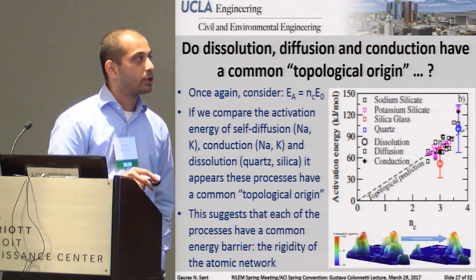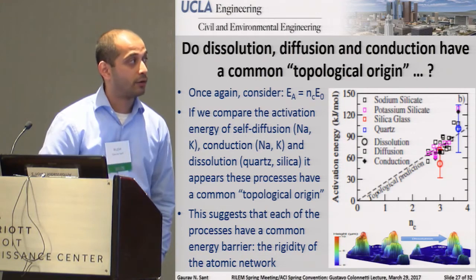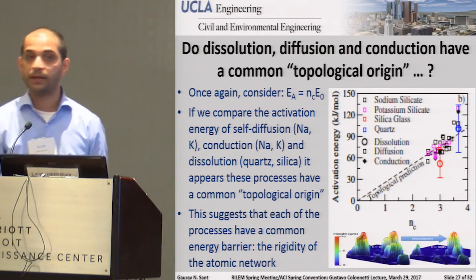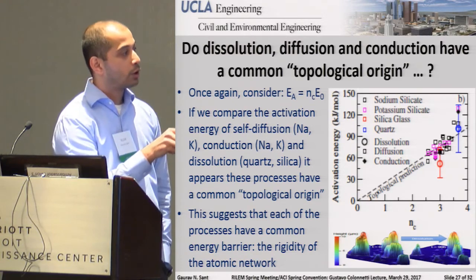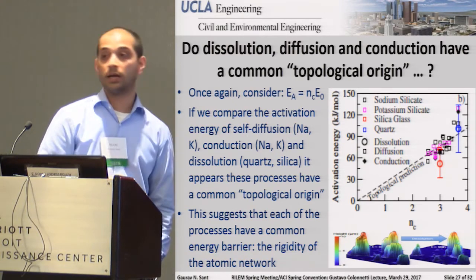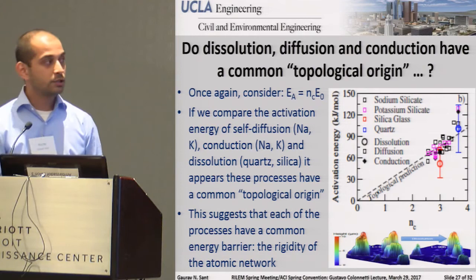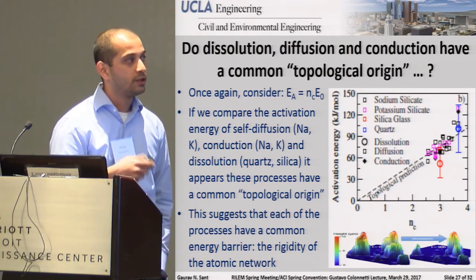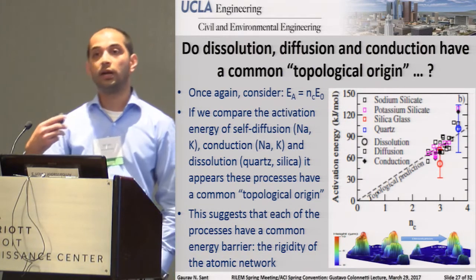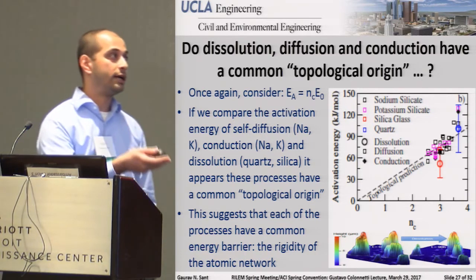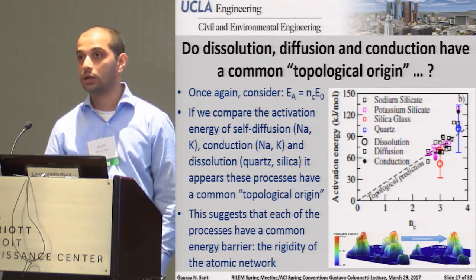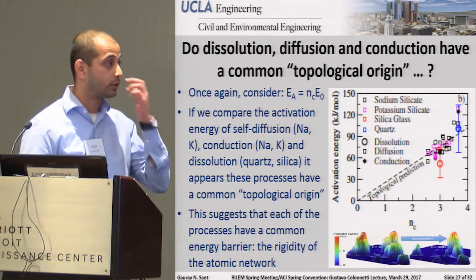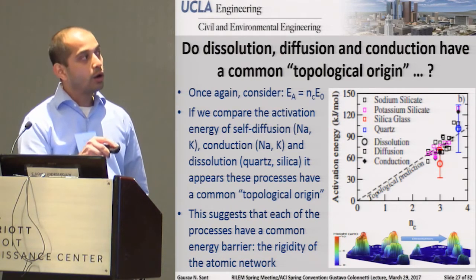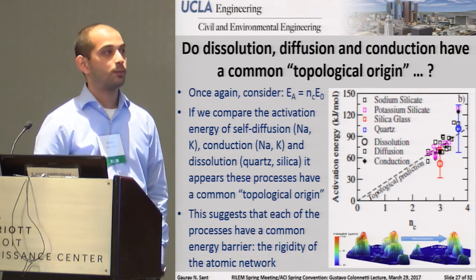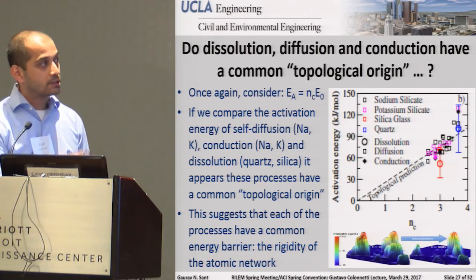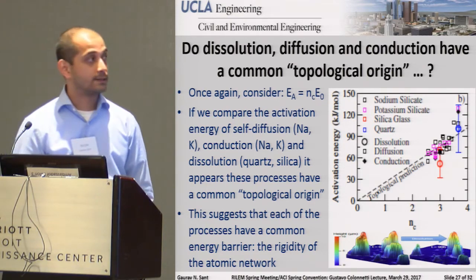Now, this is really quite good because what it suggests is that, first of all, these processes seem to have a common topological origin, or an origin which is based in the network, so to speak, but it also suggests that there is a common energy barrier, and that's really the rigidity of the network. A lot of these processes which are related to transport, for example, related to proton penetration or ion hopping or hydroxyl attack, where hydroxyls start to penetrate into solid structures, are all related to a key network transport step, which is quite good because it starts to give you an indication of where all of these things are.